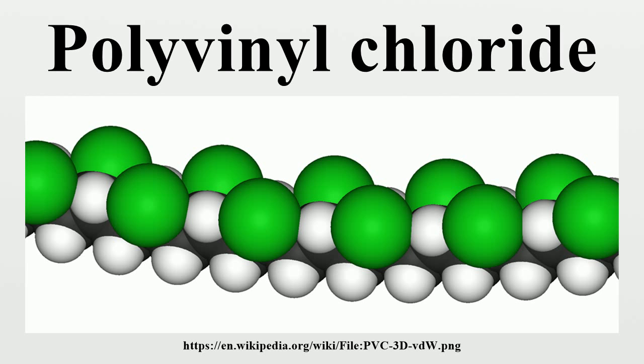Production: polyvinyl chloride is produced by polymerization of the vinyl chloride monomer, as shown. About 80% of production involves suspension polymerization. Emulsion polymerization accounts for about 12% and bulk polymerization accounts for 8%. Suspension polymerization affords particles with average diameters of 100 to 180 micrometers, whereas emulsion polymerization gives much smaller particles of average size around 0.2 micrometers.